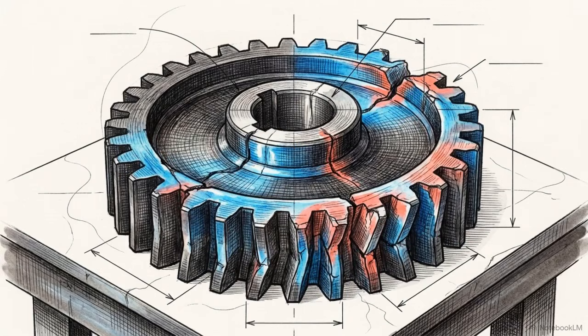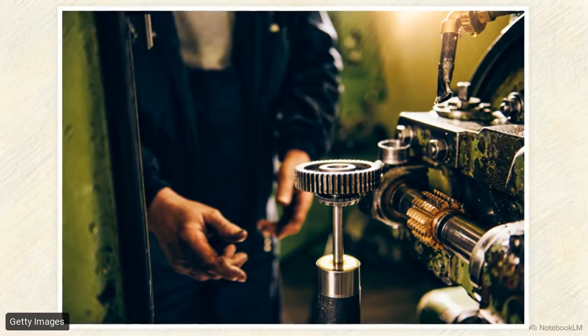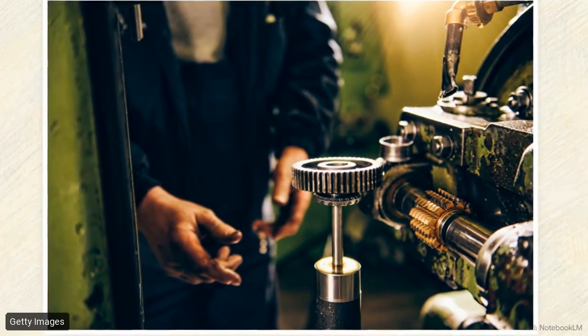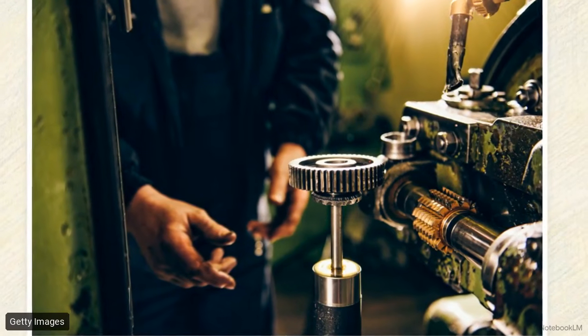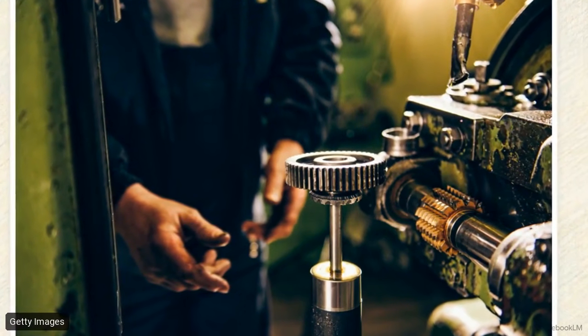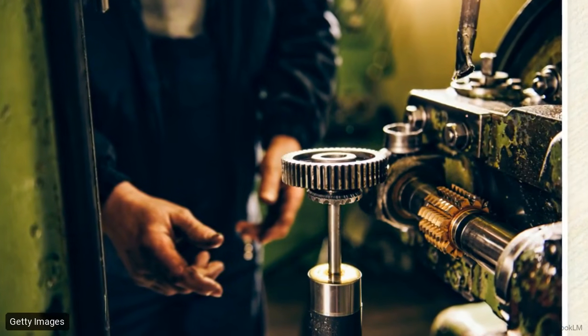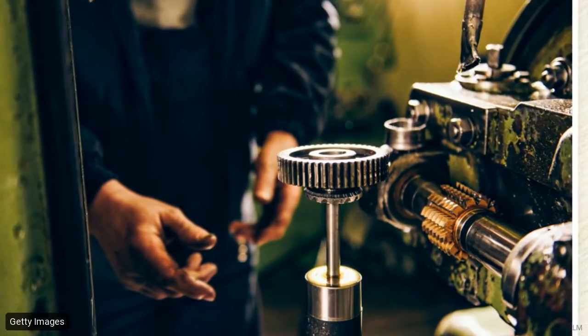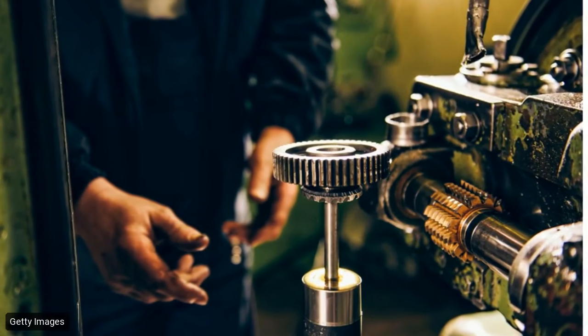To lock that diffused carbon in place and achieve the final extreme surface hardness, the steel requires a mandatory second step: rapid cooling, known as quenching. But rapid quenching carries a severe engineering trade-off. The sudden thermal shock introduces a high risk of physically warping and distorting the component. Despite this distortion risk, carburizing creates a hard exterior shell over a tough, ductile core. This specific combination is ideal for heavy load applications, like industrial gears, that face intense surface friction alongside constant core fracture risks.